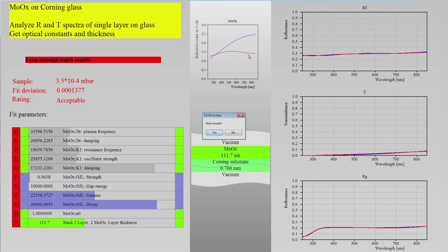It could be a broad interband transition as well, or it could be isolated charge carriers which cannot really move through the whole material, so they are confined in certain regions of high conductivity, and they are blocked by regions which have a very low conductivity, so they cannot easily move through that barrier. That would lead to a high polarizability, and that can be described by a very broad so-called Kim oscillator, which I used. For all the oxidation states, I used the same model.